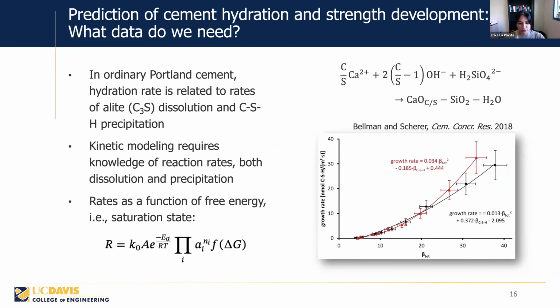So so far I've shown our work on the morphology and also the structure of MSH. When we try to predict cement hydration and strength development, what other data do we need besides those? In ordinary Portland cement, the cement I showed earlier, the hydration rate, which also controls the rate of strength development, is related to the rates of alite, the C3S dissolution, and CSH precipitation. So if we'd like to predict the microstructure evolution and the phase assemblage evolution, we can do what we call kinetic modeling. However, this requires knowledge of reaction rates, both dissolution and precipitation.